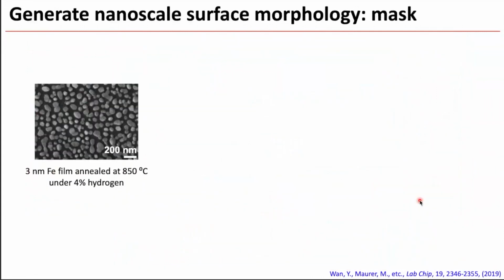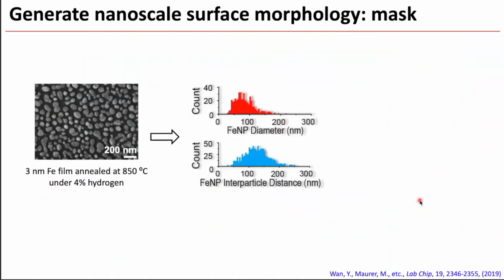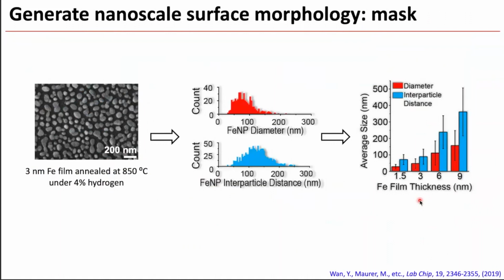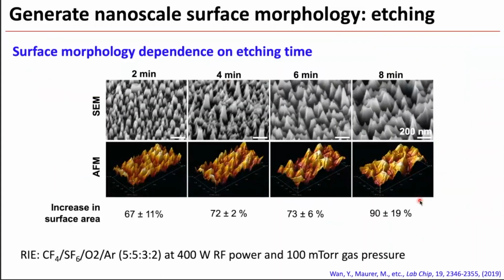So to create the nanoscale surface morphology, we use a technology we developed. Basically, we have a thin metal film on a silica wafer, and then we do thermal annealing in the presence of hydrogen. The thin metal film will form nanoparticles on the substrate. And then we can characterize the size and the interparticle distance of this substrate. And then we use this substrate as an etching mask to etch the silica surface. So we use RIE dry etching, and then we can control the etching condition to achieve certain desirable surface morphology.